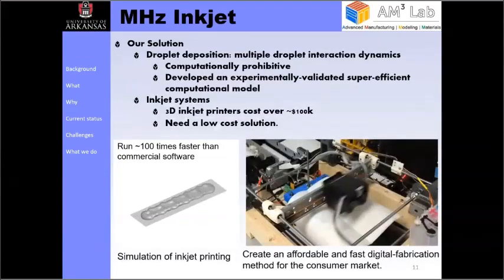Along this line, we have also studied some other aspects of inkjet, and one of those is droplet deposition. When the droplets come out of a nozzle, we want to be able to see how they evolve and form different patterns. It turns out this is very computationally expensive, and commercial software cannot simulate it. So we developed an experimentally validated numerical tool that can help us simulate this whole process. As you can see on the left side, we show an animation of several droplets interacting together. This is actually the first time this has been done. It runs about 100 times faster than commercial software, which enables us to simulate this droplet deposition process.